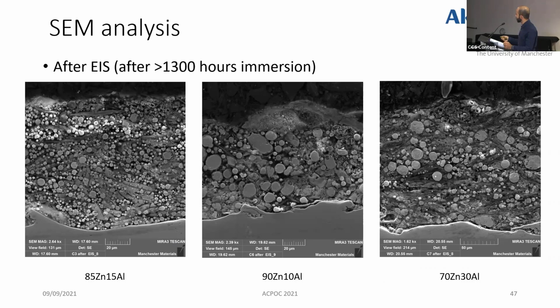What to note here is for 90 zinc 10 aluminum, there are some paths inside the coating in some local areas, which may transfer the corrosion product to the surface and expose some of the fresh zinc particles to offer galvanic action. And that can be seen here around each particle, where there is a small amount of zinc oxide, which may offer the galvanic action for some time.